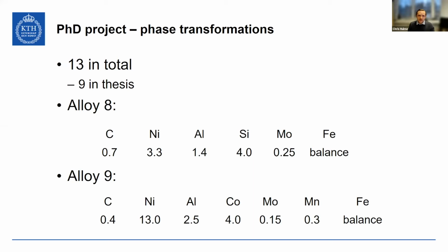And another, which was something I came up with myself, which was to reduce the carbon content and increase other austenite stabilizers. With the idea being that we could minimize the precipitation of carbides and maximize the stability of any remaining austenite through other alloying additions like nickel and cobalt. So I pushed it as high as I dared with nickel and cobalt, using aluminium instead of silicon to help drive the bainite transformation and suppress cementite at the same time. Hoping that one of those two would work.